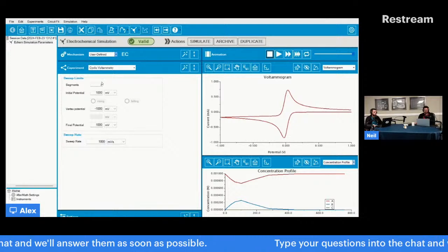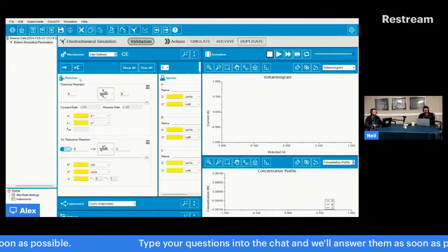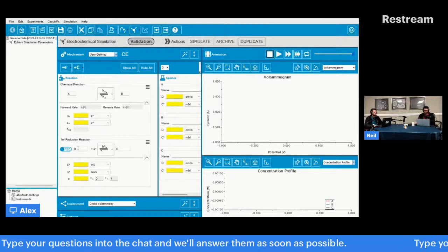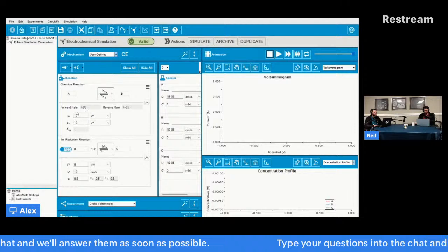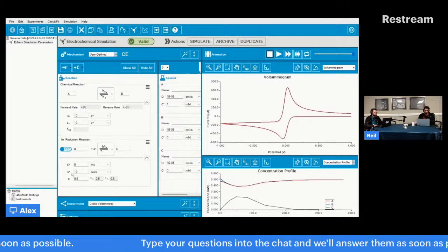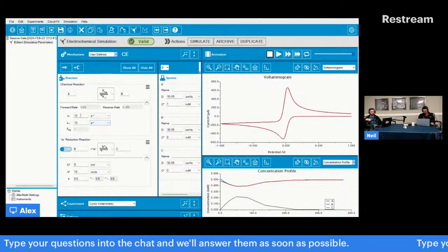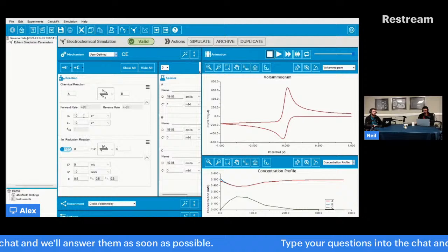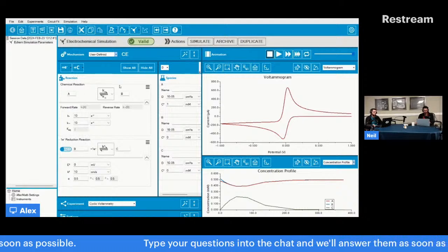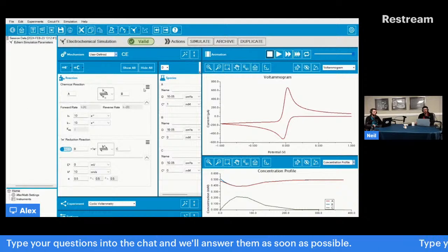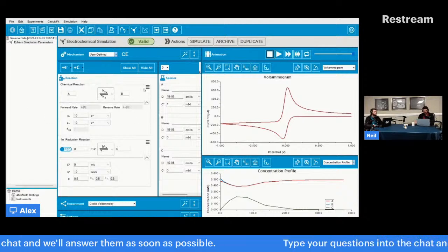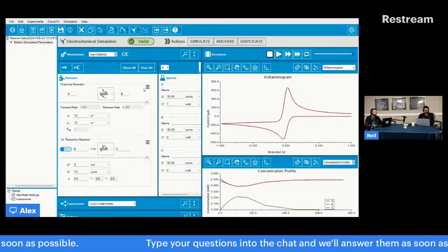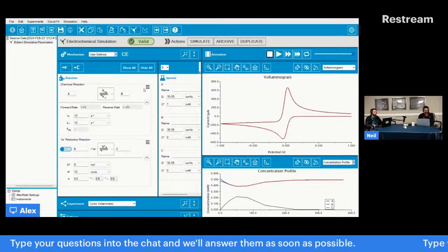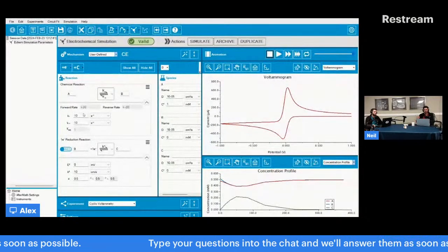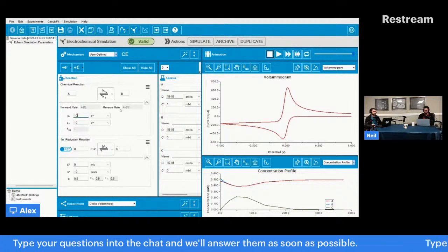Now, if you were doing something like a CE reaction, this is the case where you have the chemical step first, and then you have the reduction reaction. So again, let me autofill this, and if we simulate this, you'll probably get something like this. And what you can at least do, and what some people have done, is that this kind of reaction in some cases is maybe an acid catalyzed reaction. So what a lot of people do is they'll change basically the equilibrium, the rate constants, using stronger acids with lower pKa's to get this reaction to be something like this.